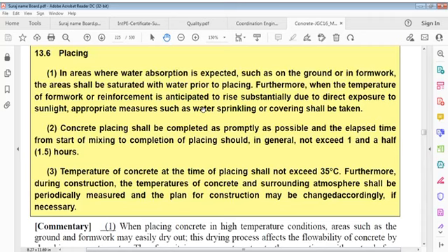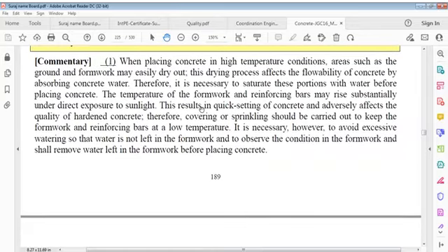Concrete placing shall be completed as promptly as possible, and elapsed time from start of mixing to completion of placing should in general not exceed 1.5 hours. Temperature of concrete at time of placing shall not exceed 35 degrees Celsius. Furthermore, during construction, temperature of concrete and surrounding atmosphere shall be periodically measured and planned, or construction may be changed accordingly if necessary. When placing concrete in high temperature conditions, areas such as ground and formwork may easily dry out. This drying process affects flowability of concrete by absorbing concrete water. Therefore, it is necessary to saturate these portions with water before placing concrete.